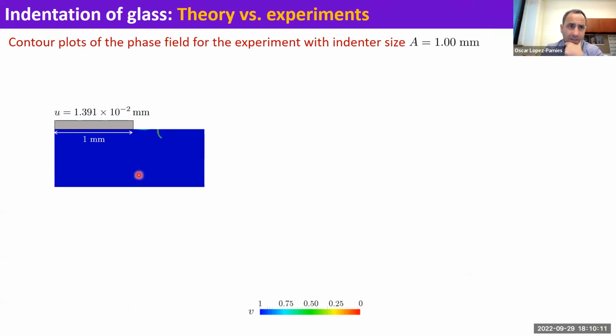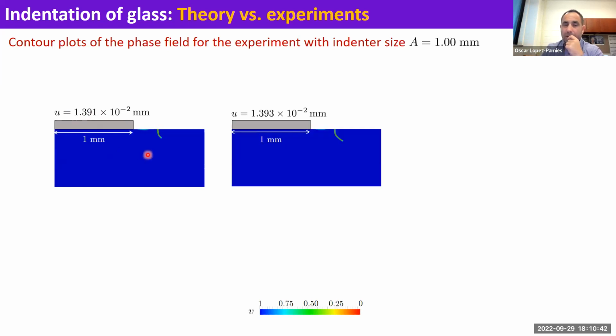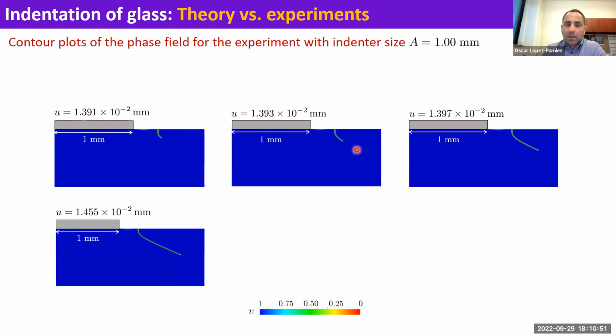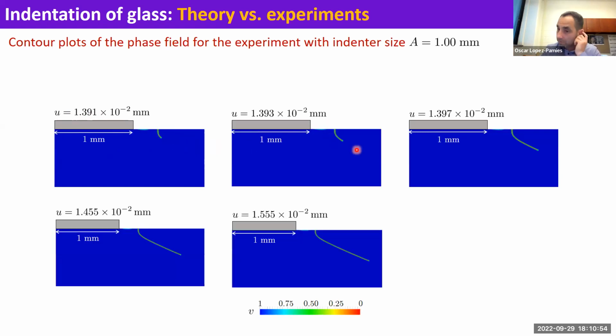this is what we get. This is half of the specimen. This is a simulation, and these colors here are indicating the presence of a crack. So the theory says that at this value of the applied displacement of the indenter, you nucleate a crack. Indeed, you nucleate a crack. There is a ring crack, right? You should think of this as an axisymmetric specimen. If you think about a revolution along the vertical axis, you will see that it becomes a ring crack. And this is what happens when you continue to push the indenter down. After you nucleate a crack, the crack turns and it becomes a conical crack. These are just snapshots of what happened according to the simulation.